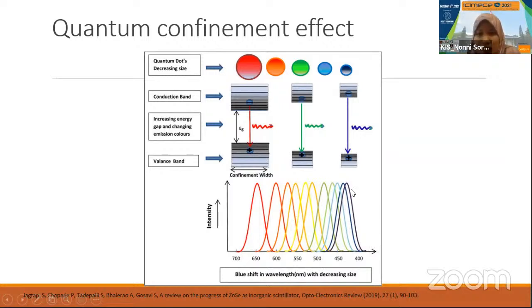The blue shift means that the quantum dot itself is more sensitive in the UV region. So by modifying the size of the quantum dot, we can tune the energy gap of the quantum dots and also the shift in their wavelength. We can engineer the size of the quantum dots for them to be sensitive to either visible light irradiation or UV light irradiation. So the size of the quantum dot gives these unique properties.